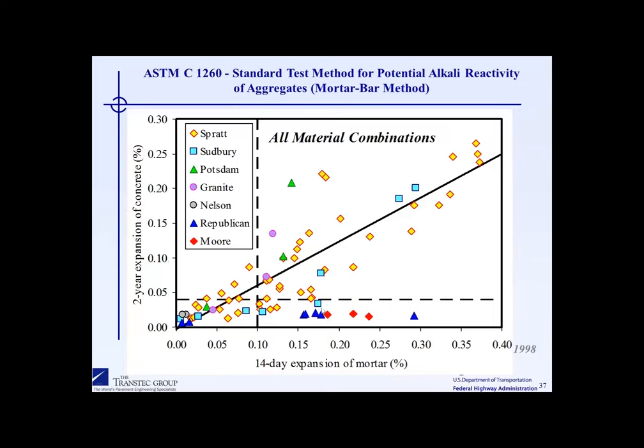Here's some additional data, just kind of showing some similar results. Again, I'm showing the mortar bar versus the two-year concrete prism test. This black line here is a line of equality in terms of expansion. And what you're seeing here is that there's a reasonable correlation between the two tests, albeit there will be cases where we will pick up some of these bad actors in both the bottom right and the upper left quadrant.